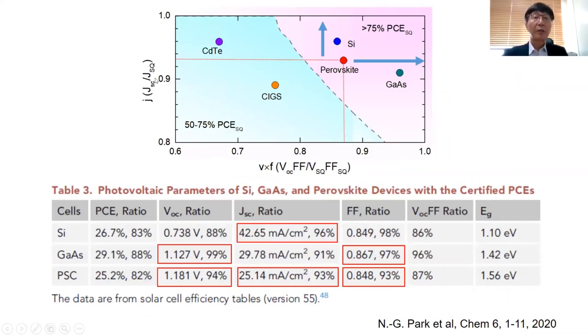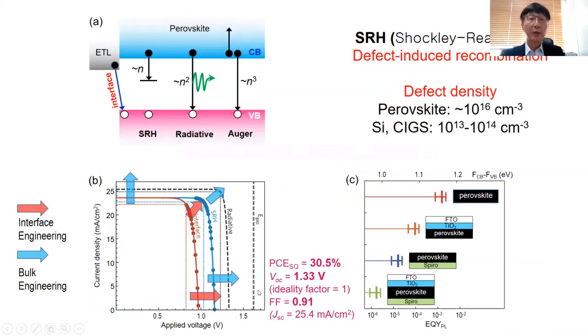However, in terms of the Shockley-Queisser limit, we still need improvement of the short circuit photocurrent density, and a significant increase in open circuit voltage and fill factor as compared to silicon and gallium arsenide solar cells. In order to increase the open circuit voltage and fill factor, usually we have to control the recombination. There are 3 different recombinations here, and the SRH recombination is critical in determining the open circuit voltage. In addition, the interfacial recombination is very critical in determining the open circuit voltage. For instance, if you manage the interfacial engineering, then you can increase the open circuit voltage and fill factor. However, there is no significant change in short circuit photocurrent density.